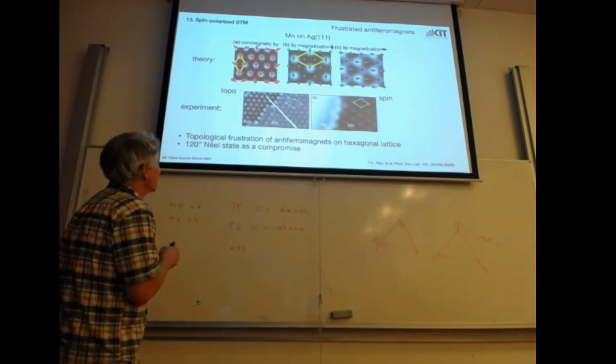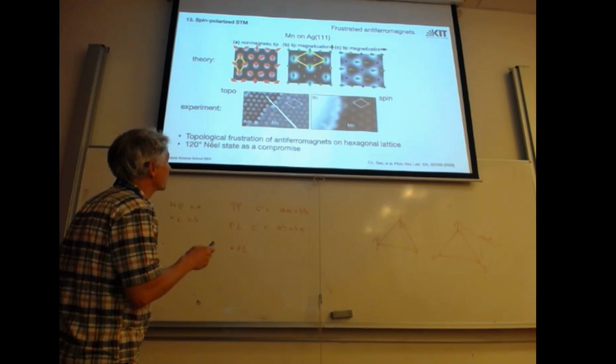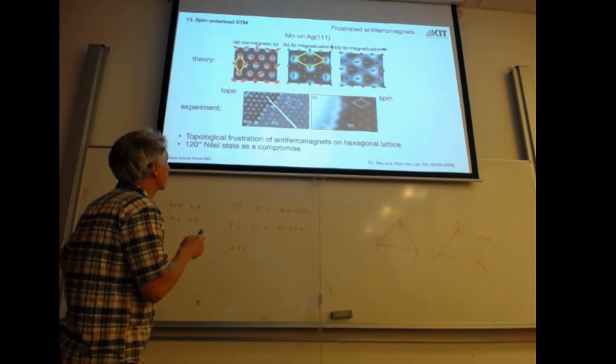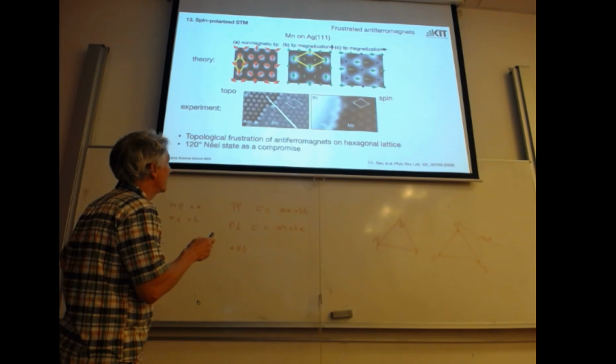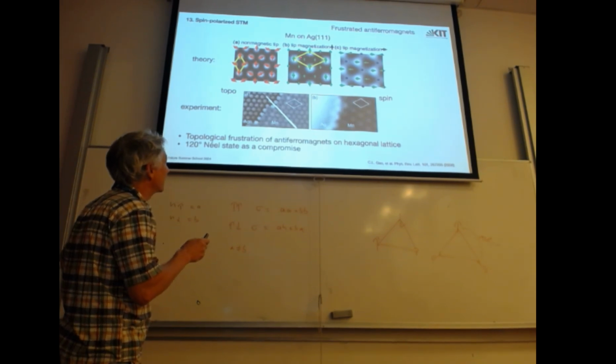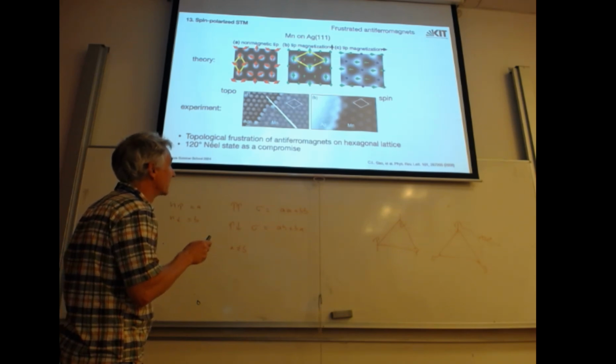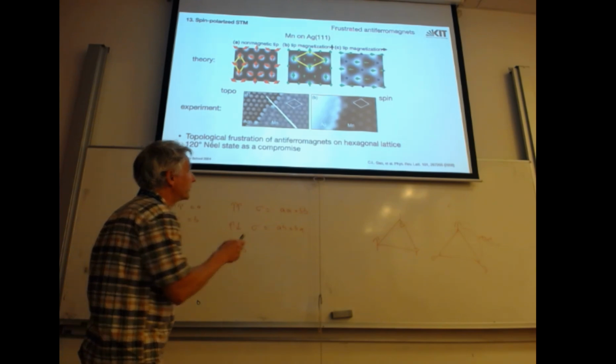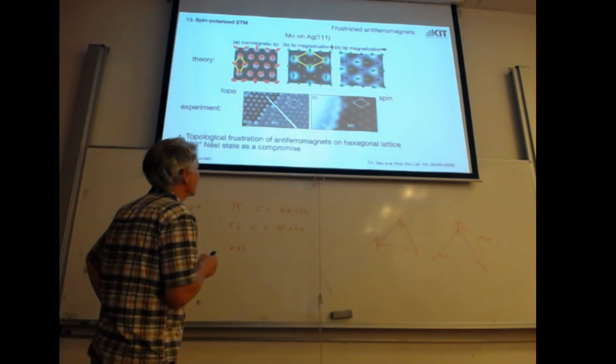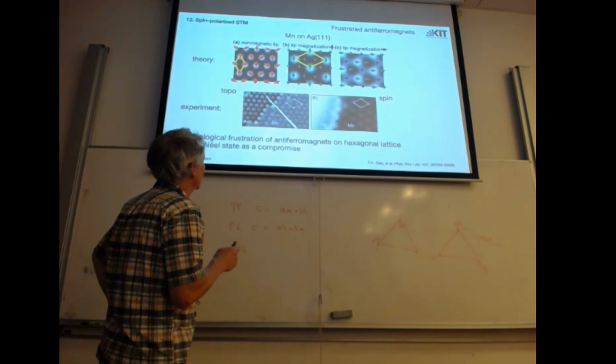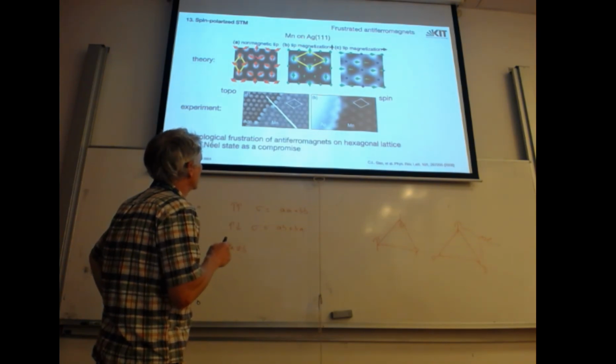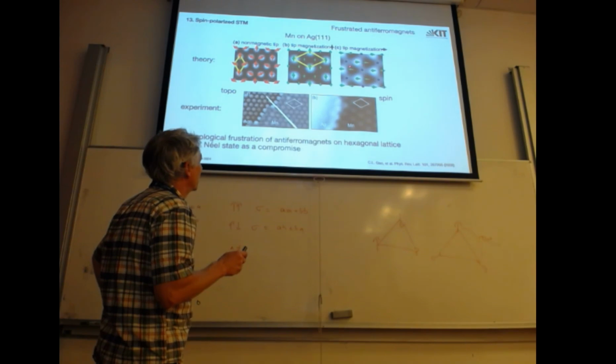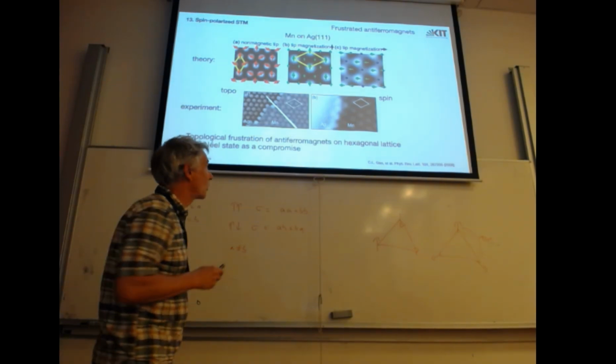And if we have a tip, for example, that is magnetized in this direction, parallel, parallel, parallel, parallel, and these are nearly anti-parallel, so these atoms appear bright and those darker. Or if the tip is magnetized, for example, in this direction, then you see that this one will be brighter, some of them intermediate, and some of them anti-parallel, almost anti-parallel.